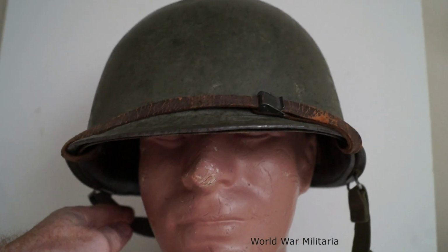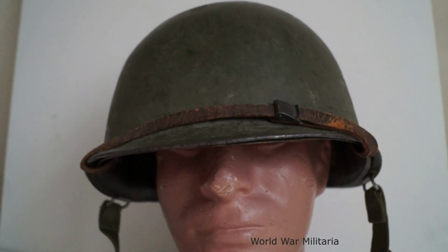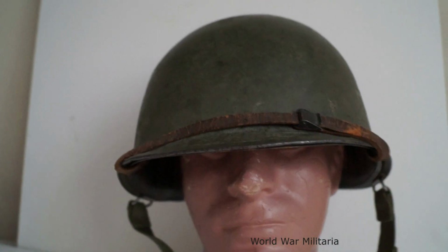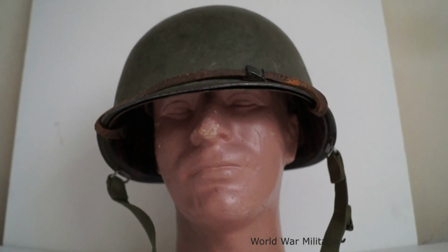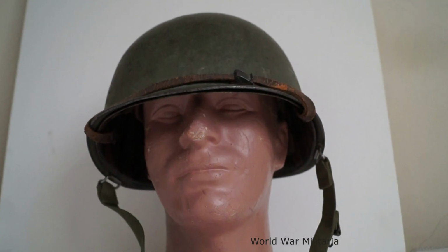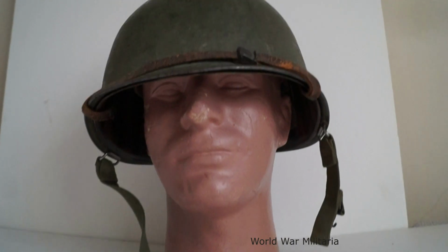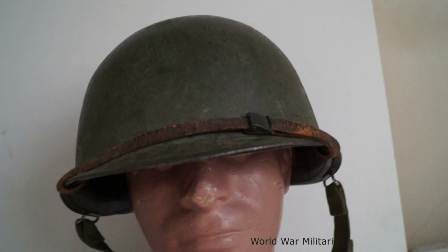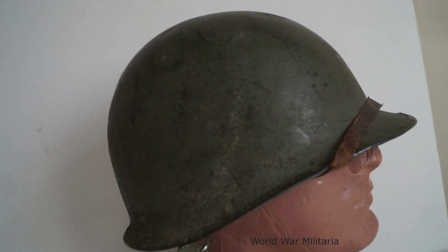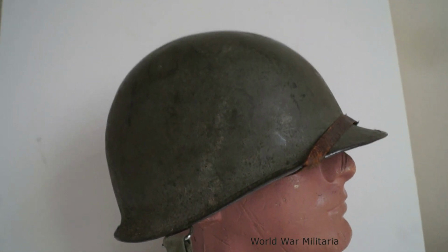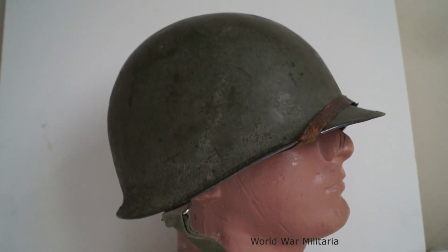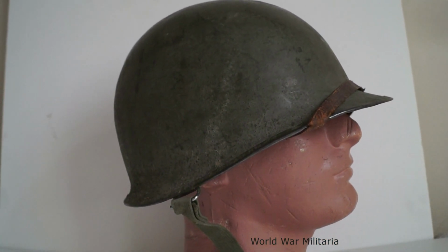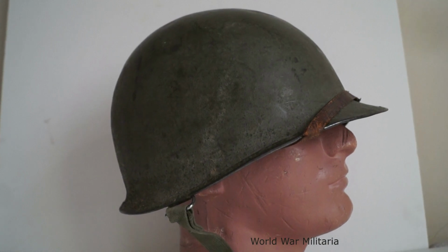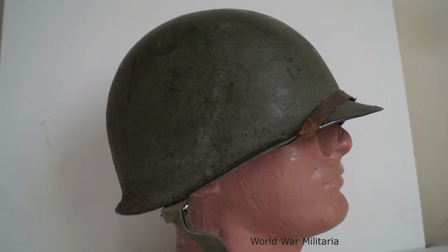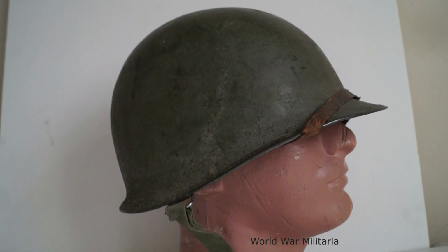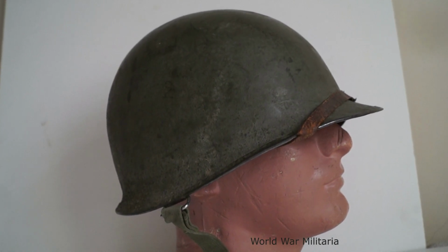The pot-shaped steel shell was drawn out of a 16.5-inch circular piece of non-magnetic Hadfield manganese steel. A stainless steel rim and chin strap loops were welded to the shell, after which it was coated with a dual olive drab green on the inside and outside. The paint on the outside was mixed with cork particles, which gave the steel shell a coarse appearance. The price for an M1 steel shell initially averaged 90 cents.